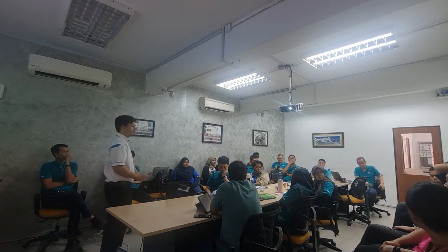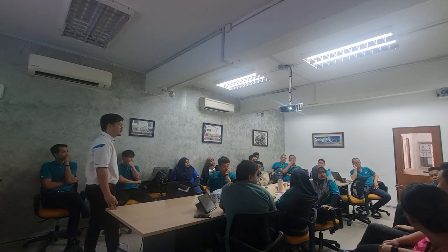Because after you steam, actually your porosity increases. In the microstructure, porosity increases, and the strength increment is less. For comparison, steam curing compared to water cure, actually the minimum requirement is 90% of your target. Let's say target 50, you only get 90% of 50, which is 45. That's why if you want to use steam curing, you need to top up your additional strength so that after you steam, you pass your 50. That's the drawback because after you steam, the porosity increases. Compared to UHPC, the one Dura is doing is a different story.